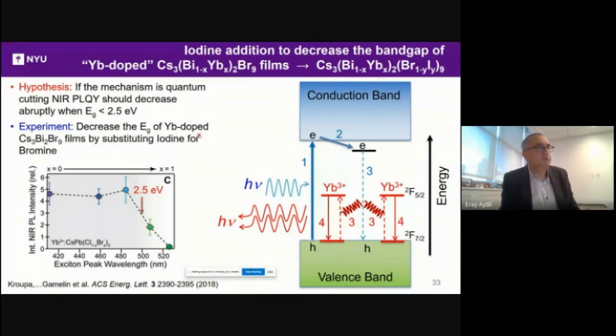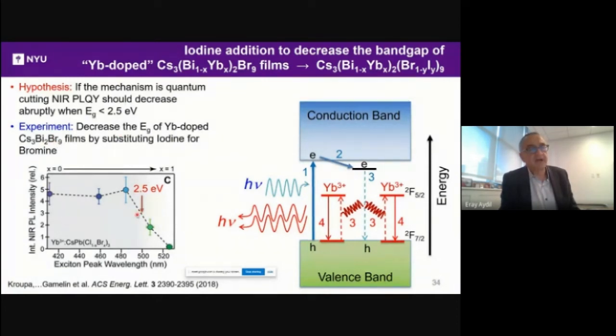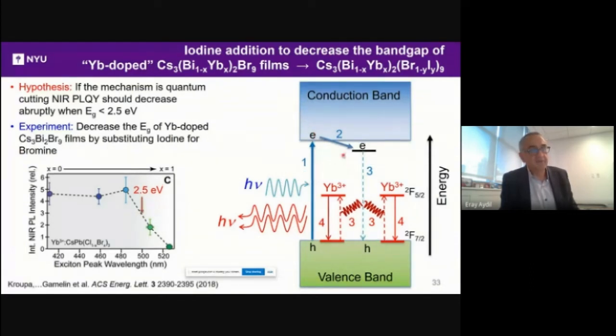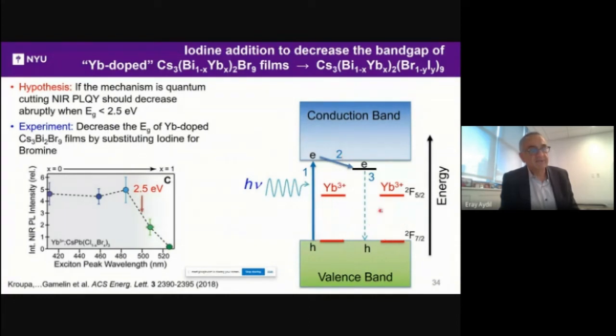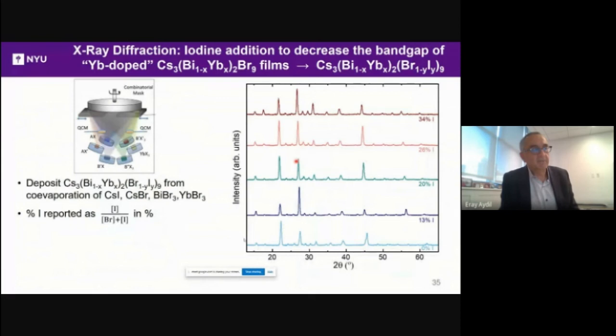So we're going to decrease the bandgap of ytterbium-doped cesium-3 bismuth-2 bromine-9 by substituting with iodine and see what happens. The idea is to decrease that conduction bandgap, so that we stop that emission and the photoluminescence quantum yield goes down. So we do the same thing, except now we turn on yet another source, and we put in cesium iodide in addition to cesium bromide. I'm going to report the percent iodide as iodide divided by bromine plus iodine, okay? And so we went up from 0 to 34% without disrupting the structure of the material.